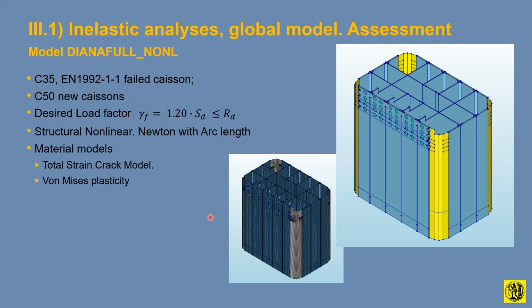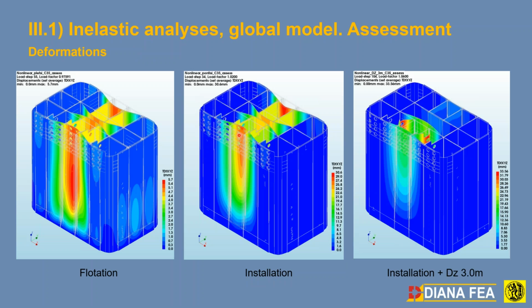So we do define all the load cases times 20% up for the assessment. We use Diana, the Total Strain Crack Model, and von Mises plasticity for the rebar, the embedded rebar, and a nonlinear solution using Newton tangent stiffness with arc length search. And okay, these are the results. First of all, the deformations in millimeters of the nonlinear analysis, flotation, installation, and also the accidental installation plus 3 meters in the center.